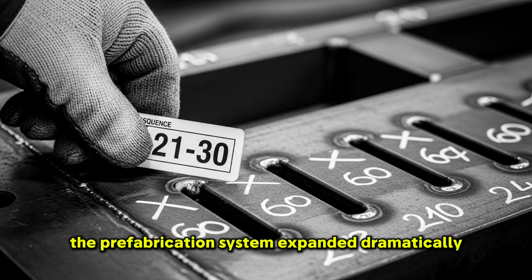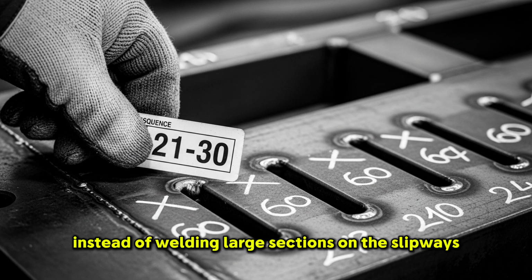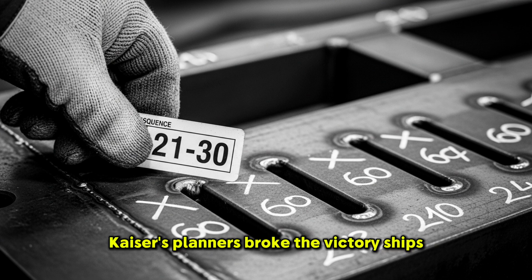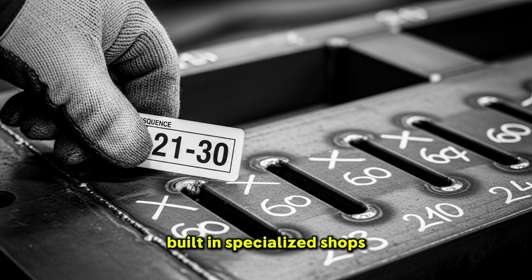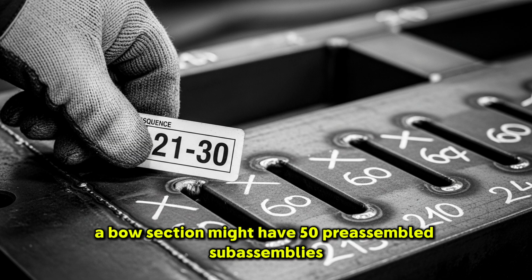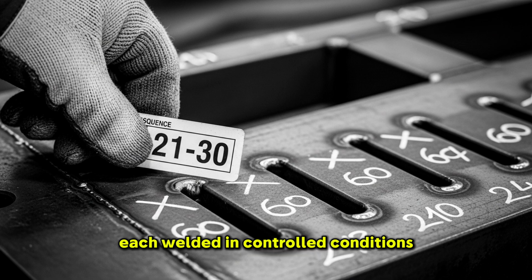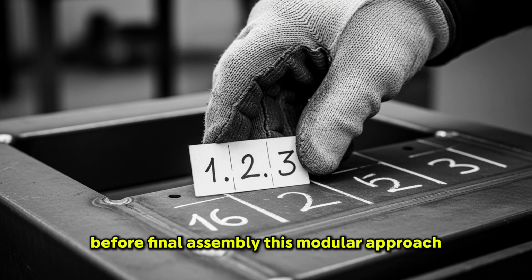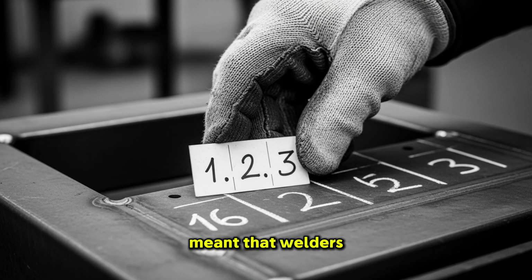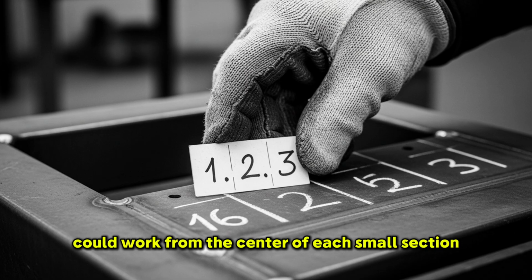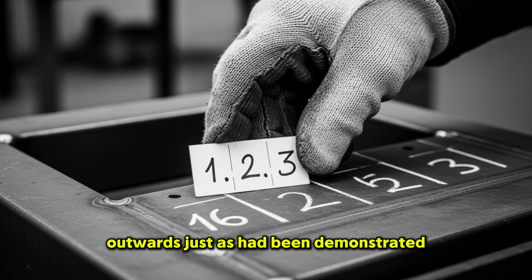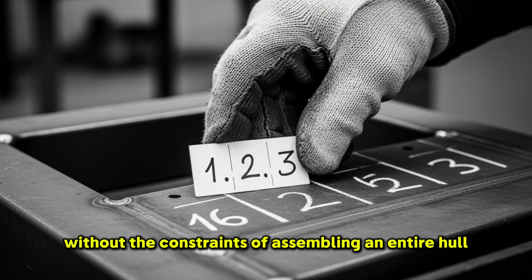The prefabrication system expanded dramatically. Instead of welding large sections on the slipways where sequencing was difficult to control, Kaiser's planners broke the Victory ships down into smaller modules built in specialized shops. A bow section might have 50 pre-assembled sub-assemblies, each welded in controlled conditions using the optimal sequences, then stress-relieved in heating furnaces before final assembly. This modular approach meant that welders could work from the center of each small section outwards, just as had been demonstrated, without the constraints of assembling an entire hull.